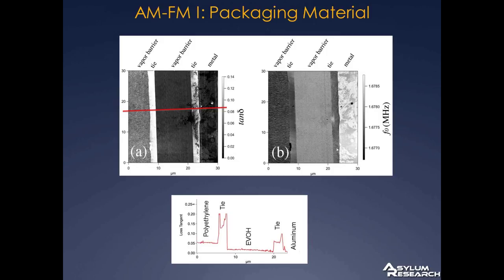And you can see here this image over here. So on this side, this is some sort of polymer. This is the tie layer, which is a flexible soft layer that connects the rigid layers. Here's another polymer. This over here is aluminum. It also has some stuff on top of it, probably water that dried from the cryotoming. But here we see a very clear frequency shift. The metal is very, very stiff, so the frequency shift is high and the polymers are low. So it does work on metals and harder materials. You do have to take into account the greater stiffness, though, and it may be that the contact area of the cantilever tip in the two different kinds of materials will be different.